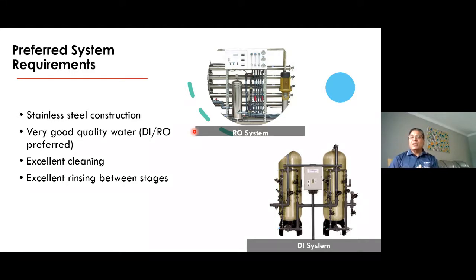Do we have to have stainless steel across the line, starting from the cleaner all the way to the post treatment final stage? Not necessarily. The recommendation is that we would use the stainless steel rinse prior to the zirconium pretreatment, and all the following rinses after that has to be stainless steel. Very good water quality. When I say very good water quality, you talk about less than 100 ppm, less than 25 ppm of chloride sulfate. DI RO is preferred. Do you have to use DI systems? I won't say that. I won't suggest it. If you can go with RO water, 25 to 50 micron, it's perfectly fine.